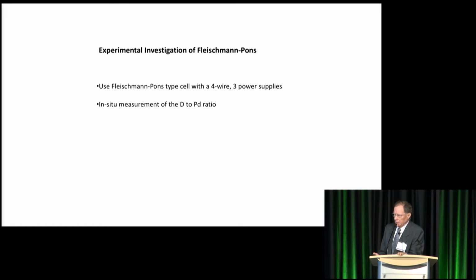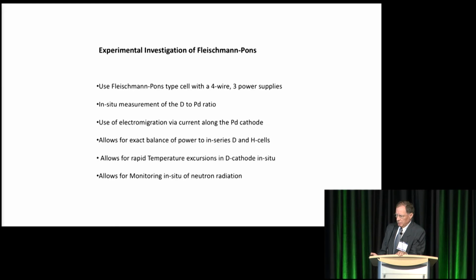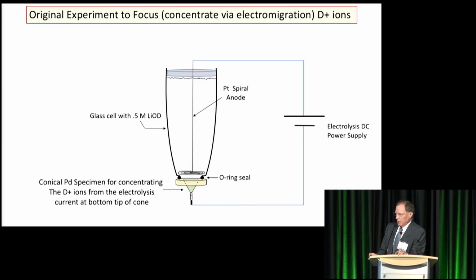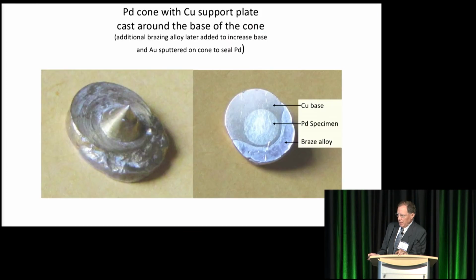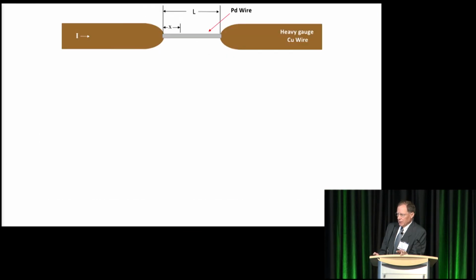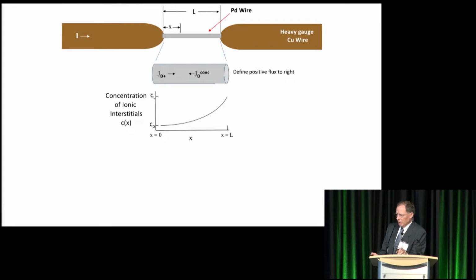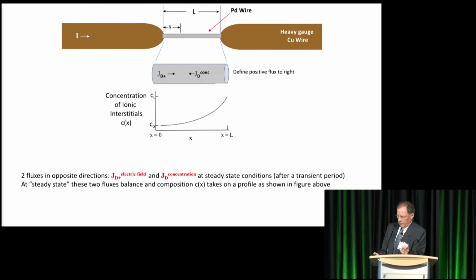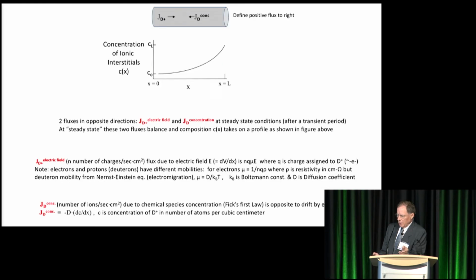All right, I'm going to talk about the experiments now, and I wanted to spend more detail, but this was my first attempt, which I'm going to skip, at using electromigration. The second attempt to use electromigration is a very small specimen, a right circular cylinder, that's connected between two heavy gauge copper wires, and the point is that if you pass the current through, you can get a concentration gradient due to the electromigration flux due to the electric field, and the back flux due to Fickian diffusion. And when these two balance, of course, you get steady state.